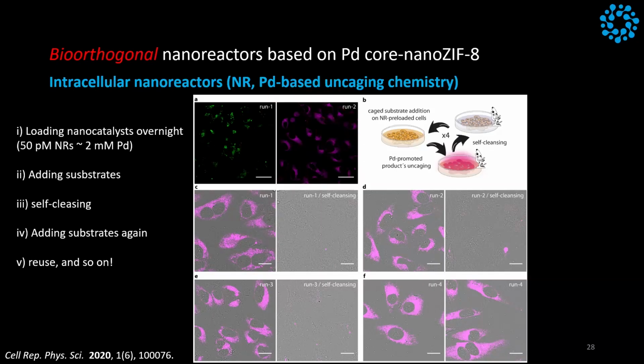And the cool thing about this is that we could do these reactions for a week. So basically, you have a cell culture with your palladium catalyst inside, and then you start adding substrate, checking the microscope, cleaning, and then when you clean, in a concentration-dependent manner, because of different chemical gradients, what you have inside the cell will go away. Then you add again the substrate and do it again. For 1 week, you can do the reactions inside the cells. And eventually what happens is that you have too many cells to do anything, and you don't have enough space. But for 1 week, you can have the palladium nanoreactors inside a cell working.